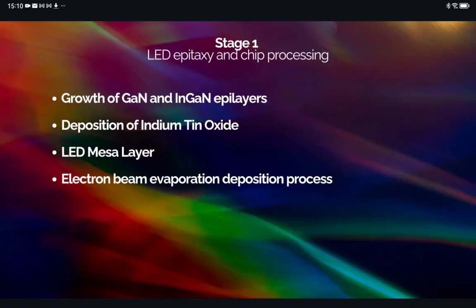In LED epitaxy and chip processing, first gallium nitride and indium gallium nitride are grown on a C-plane sapphire substrate or 111 Si substrate by metal organic chemical vapor deposition. Then indium tin oxide is deposited as a transparent current spreading layer and as an ohmic contact. The current spreading layer's function is to ensure that the injected current is spread as evenly as possible across the near surface area of the device, while an ohmic contact is to allow charge to flow easily in both directions. After that, the LED mesa is defined by the etching process and is etched all the way down to the N gallium nitride. Then P and N electrodes are deposited by electron beam evaporation.